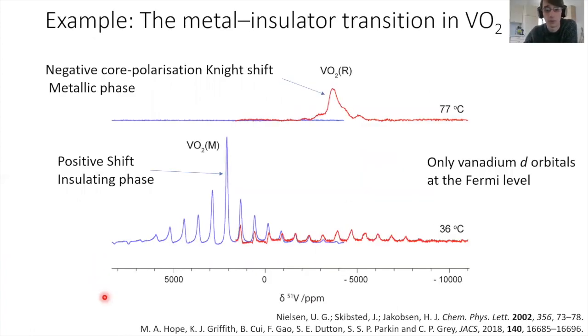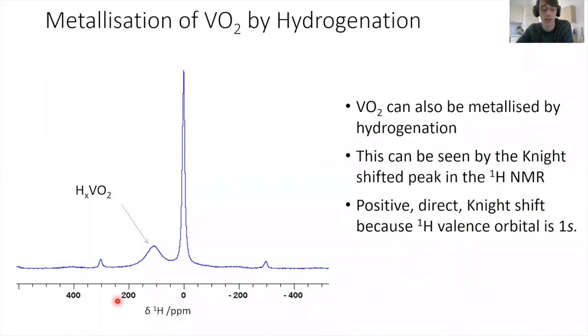So the vanadium spectrum is what I'm showing here, and this is the 7,000 ppm shift on metallization. Oh, do you mean in the case of the hydrogenation? Because that would be a better question. So it depends on the degree of hydrogenation, and if you're interested, I direct you to the paper at the bottom. It turns out that for that spectrum I showed you, this one, this was actually for a very low amount of hydrogenation.